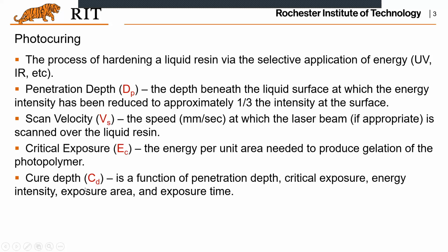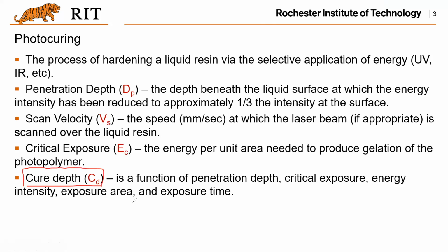The last one is the cure depth. That is a function of the penetration depth, critical exposure, energy intensity, exposed area, and the exposure time. So basically, this cure depth is what we are looking at. That will tell you what the width of the laser trace is, and that is a function of all these parameters, and this is usually what we are looking at for solving some problems.